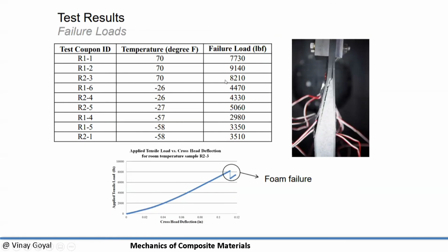So something was going on that needed to be understood, because in the actual application, the failure load is actually way smaller than if you tested at room temperature, which is not intuitive. You'd expect that the test configuration somehow will be the critical condition, and it is in this case, but it doesn't encompass all the other conditions, room temperature and so forth. And so, as a consequence, it's important to instrument the samples really well, so when failure occurs, you can pick it up and then assess it.